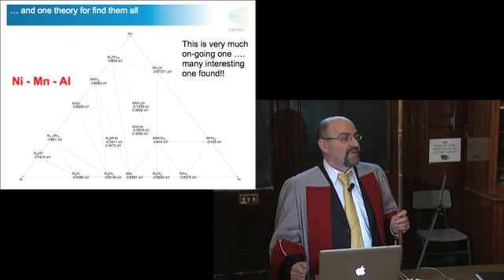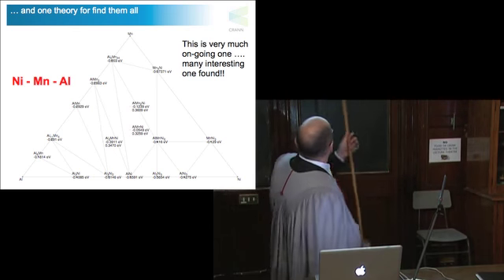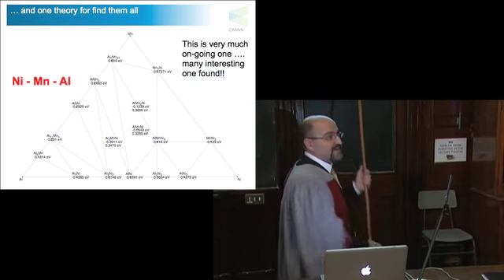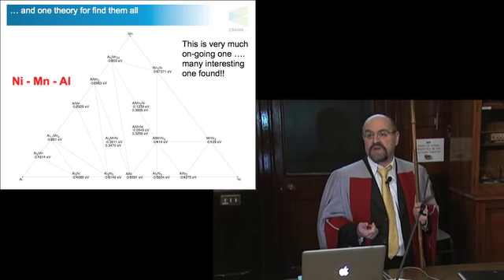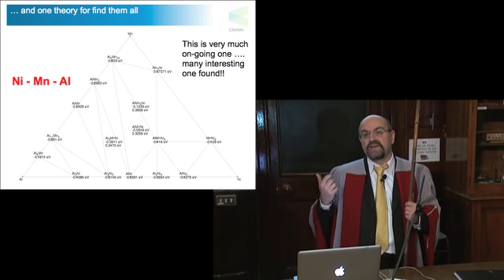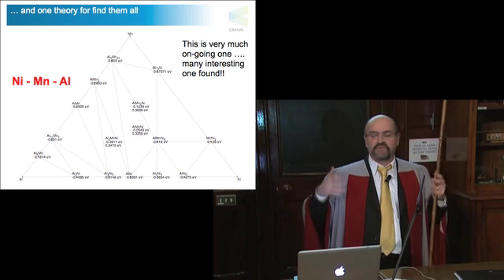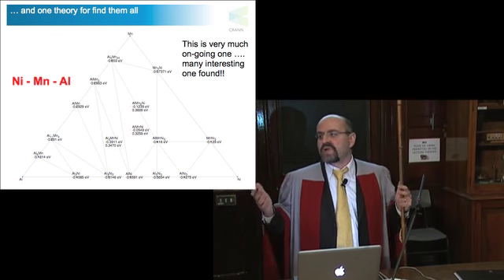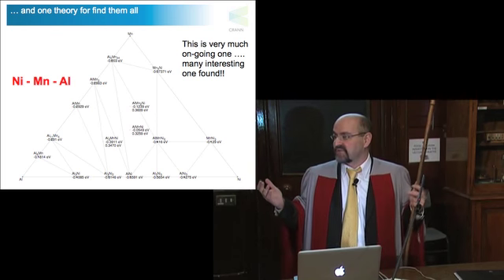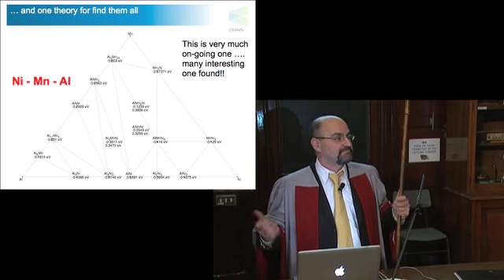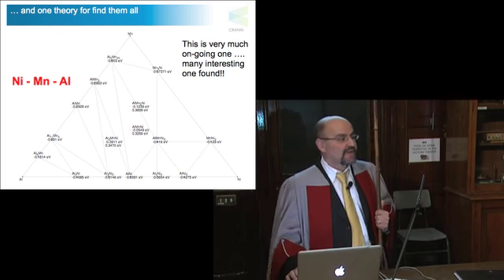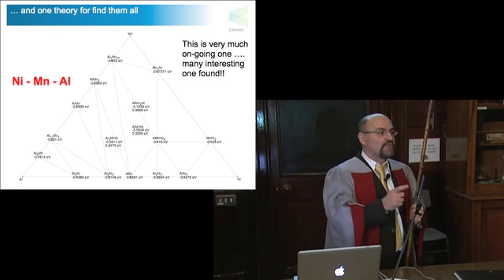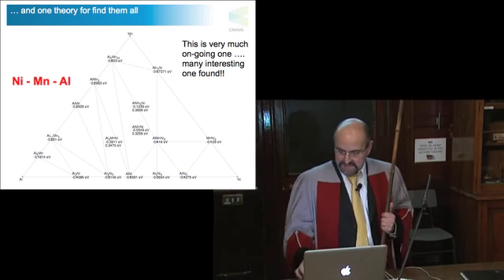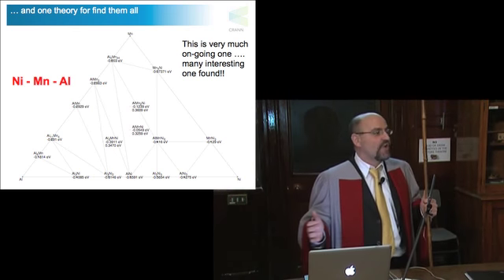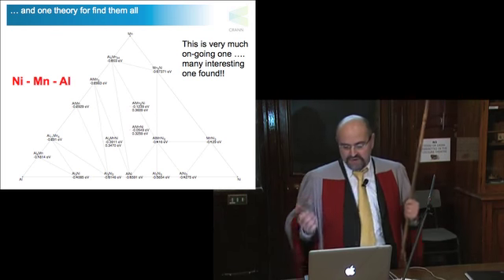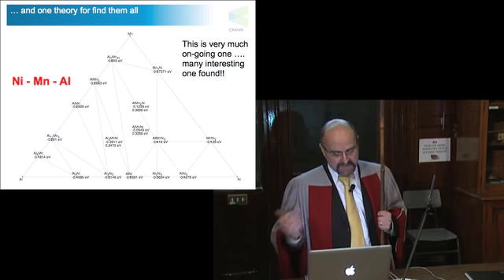However, these calculations are very painful. For instance, you see here that we have 4 candidates to start. Only one, when you go through this scrutiny, is going to form, which essentially means that likely over these 300-whatever thousand, you are probably going to have 10, 15 of them which are useful and can be made. So, a sad story, but it is certainly much quicker than asking you to synthesize all the 300,000. So this is very much ongoing. We're doing a lot of screening now for all sorts of reasons, and I think we are finding a lot of interesting things.